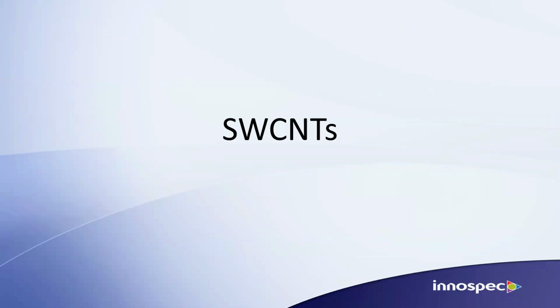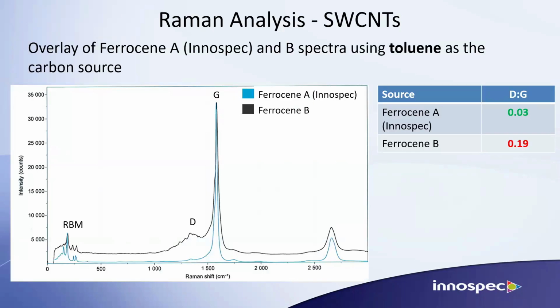Now we'll take a look at the Raman spectroscopy results for single-walled carbon nanotubes produced with the two ferrocene sources. Here we again use the direct injection method with toluene as the carbon source, keeping all the other parameters the same, again apart from the ferrocene source. The key difference compared to the multi-walled carbon nanotube experiments is an elevated growth zone temperature and addition of hydrogen, as well as some thiophene in this case to promote the single-walled carbon nanotube formation.